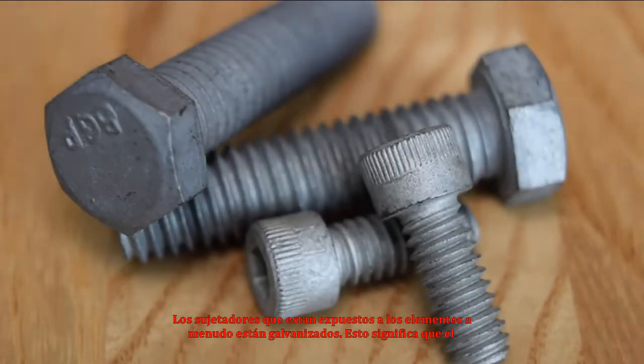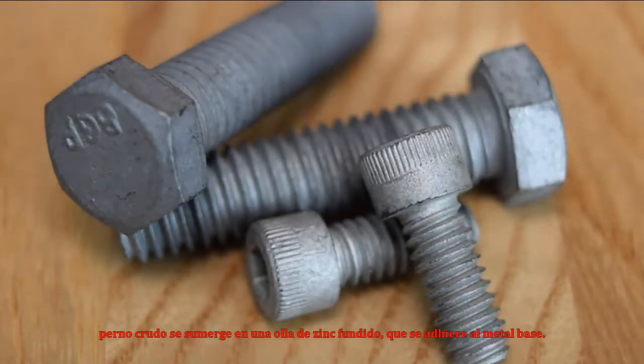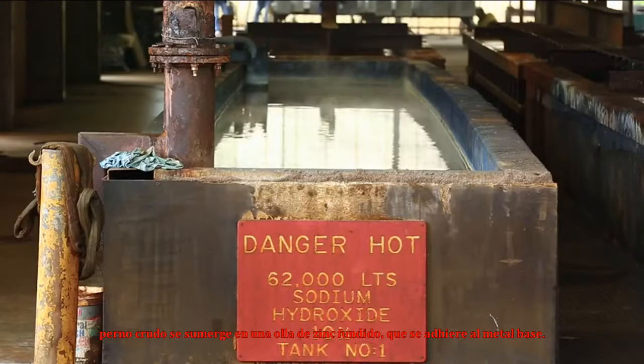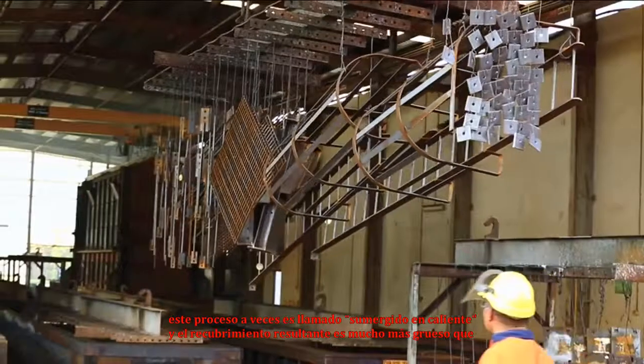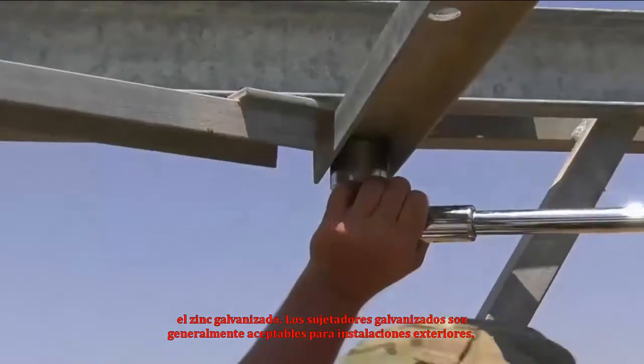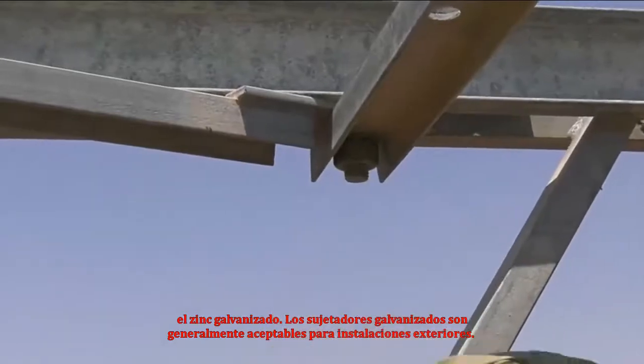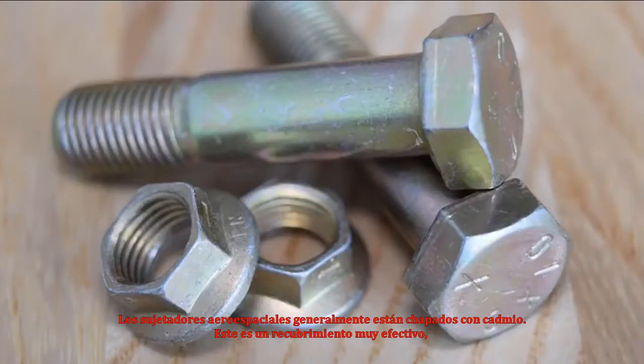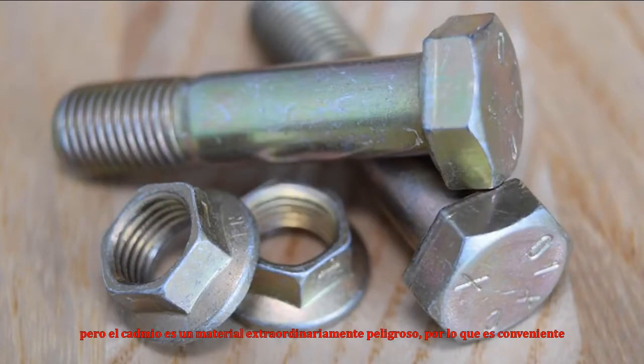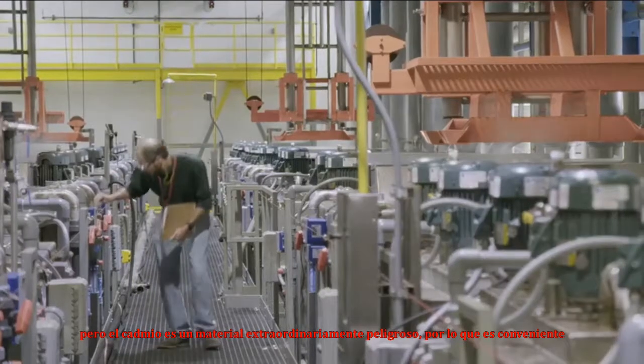Fasteners that will be exposed to the elements are often galvanized. This means that the raw bolt is dipped in a pot of molten zinc, which adheres to the base metal. This process is sometimes nicknamed hot dipped, and the resulting coating is much thicker than the electroplated zinc. Galvanized fasteners are typically acceptable for exterior installations. Aerospace fasteners are usually plated with cadmium. This is a very effective coating, but cadmium is an extraordinarily dangerous material, and these hazards are compelling manufacturers to find safer alternatives.